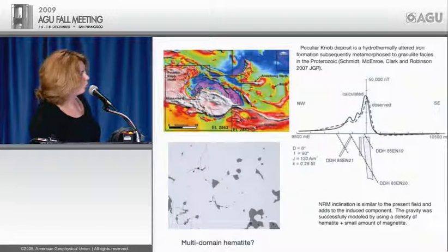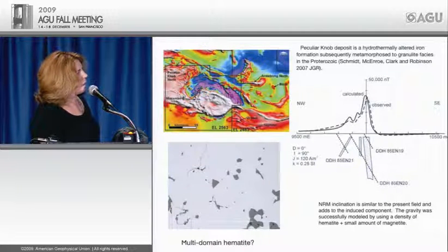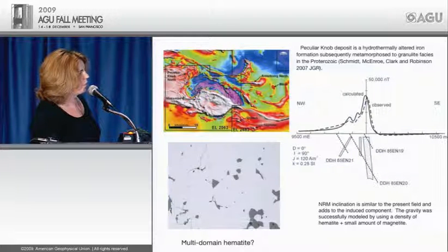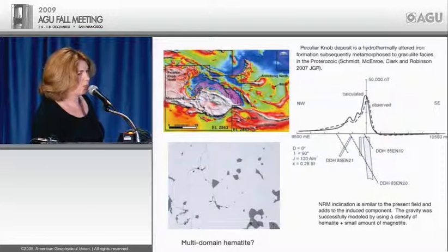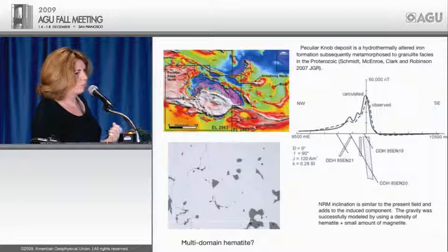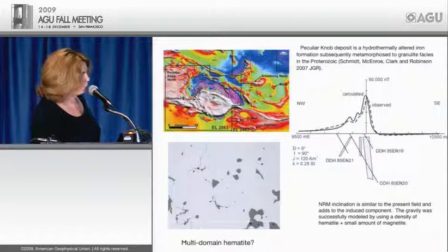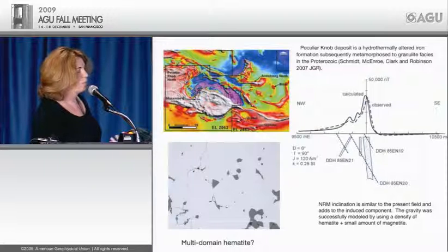If we move now to Peculiar Knob in Australia, and this is a very interesting deposit, but it's under about 40 meters of cover. And here, there were a series of drill cores that Phil Schmidt had got, and the question was, from the exploration company, whether or not they had missed the target. There was a nice big positive magnetic anomaly, and they thought they had a really big magnetite deposit. And so they had some drill cores, and they looked at the drill cores, and a lot of the drill cores contained abundance of hematite. And so they said, well, did we miss the target?